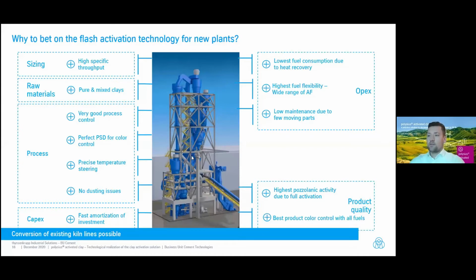So with this flash activator, we are able to activate also mixed clay minerals. This is because we don't have the very large retention time as we have it in the rotary kiln. So the kinetics is quite fast in our system. We are activating the clay within seconds, so 1 or 2 seconds, and the clay is activated. Compared to a rotary kiln, this would take much longer. So we are there in the range of minutes. So this is giving a, let's say, quite flexible system at the end, and a good to control system.